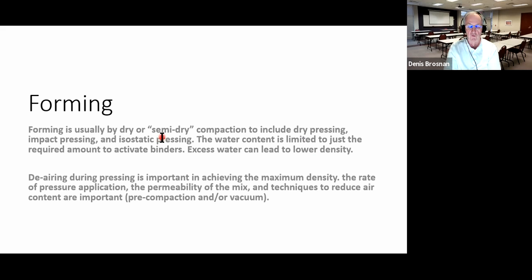Another is to use impact presses or friction presses, which will do a pre-compaction step. You can do that, of course, on a hydraulic press. Pre-compact it at low pressure, give it a dwell, let the air get out, and then press it to final density. So you'll see an example of using friction presses later on in this presentation. They basically use momentum to provide energy impact of the material. Typically, these are called bumps. And so by giving sequential bumps, we can de-air the material. In the most extreme case, people have put vacuum bells down over the press where the material is and sucked a lot of the air out before the pressing stroke takes place.